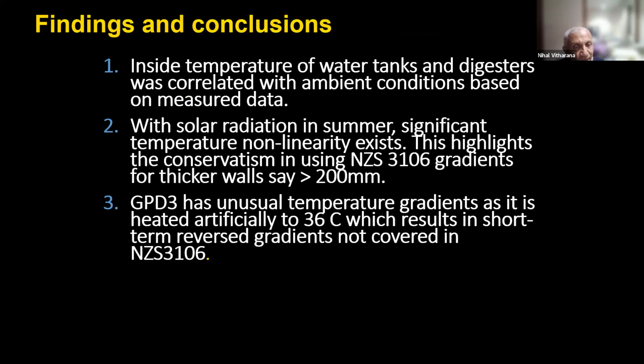Yeah, so these are the findings. Inside temperatures of water tanks and digesters were correlated in our study, but it's very important to get that in order because you can't mathematically model it, because the water and sludge come in and go out. It's an operational thing. With solar radiation in summer, significant temperature nonlinearity exists. This highlights the conservatism in using New Zealand 3106 gradients for thicker walls, say greater than 200 millimeters.